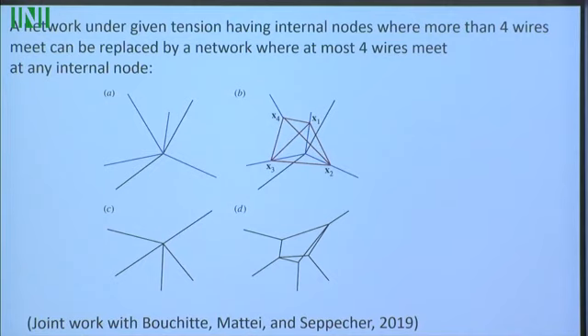The idea is that if you've got a cable web where more than 4 cables meet, you can replace it by a web where at each junction only 4 meet. This is sort of an argument by induction. Here I've got a problem where at this junction we've got 6 cables meeting, all under tension. The idea is to superimpose upon this some tensegrity structure where this is under tension, and in the absence of the cables, this would be under compression. When you superimpose them, you end up with a structure where one of these cables disappears.